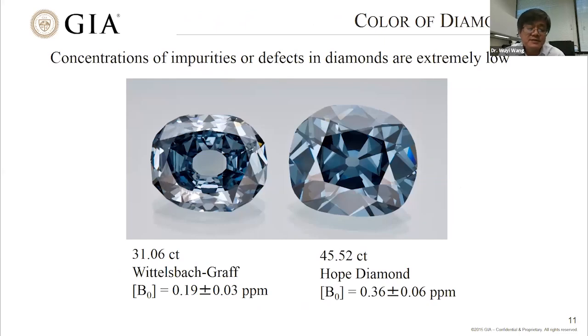Here I'm going to show you some basic principles, concepts of color of a diamond. Here what I try to show is two very famous blue diamonds due to boron impurity. One is the Wittelsbach-Graff diamond. Another one is the Hope Diamond collected in the Smithsonian Institution. Both are type IIb, colored by trace amounts of boron. What I try to emphasize here, diamond just needs very little impurity to introduce quite a lot of color. For example, in these two diamonds, the boron concentration is only about 0.2 to 0.4 ppm. That's parts per million. So a very low concentration of impurities would be able to introduce quite a lot of color in a diamond.